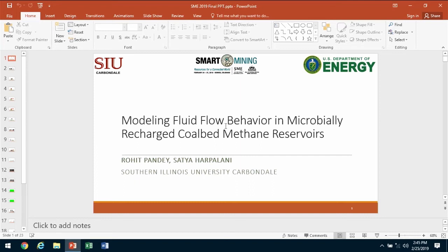Regarding why porosity decreased: in a few cases there was direct blockage of cleats due to biomass and biofilm production, but the basic observation was swelling of the matrix. In other work, we placed strain gauges on coal and bioconverted it, measuring strain as the process occurred. The swelling is usually because of imbibition of water, which leads to inelastic strains that don't go away after we remove the water. Also, CO2 is produced, and CO2 adsorption in coals is often irreversible — desorption is not the same as adsorption. A detailed study is due to accurately answer why this is really happening.